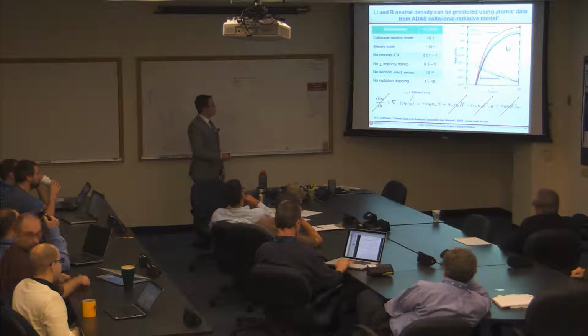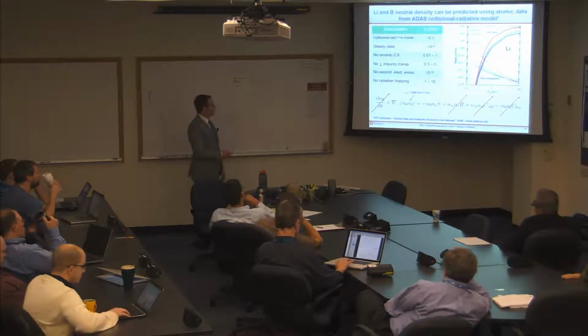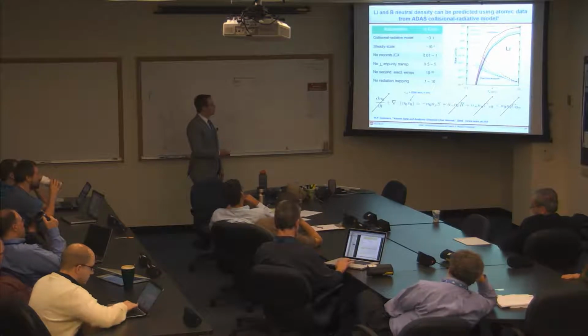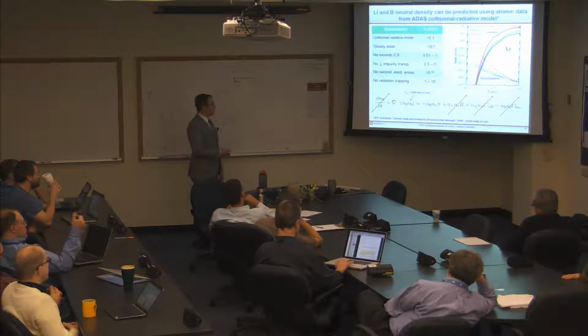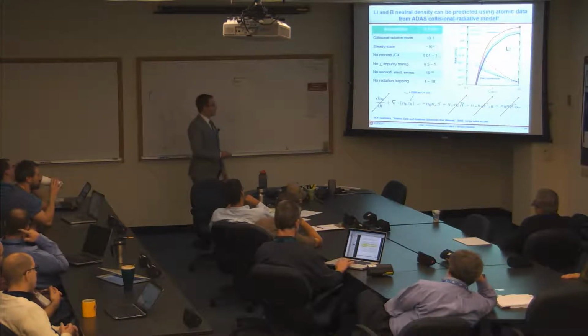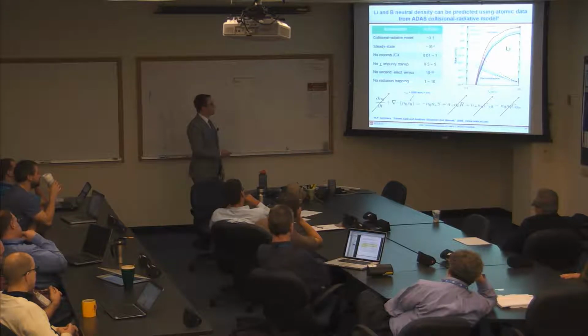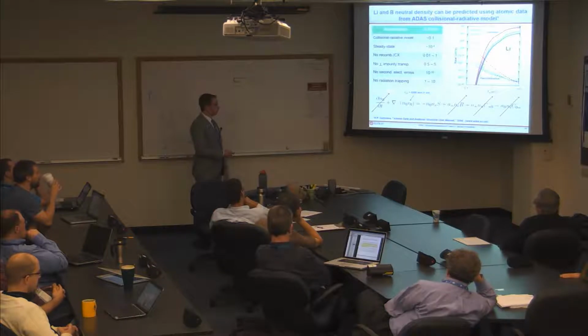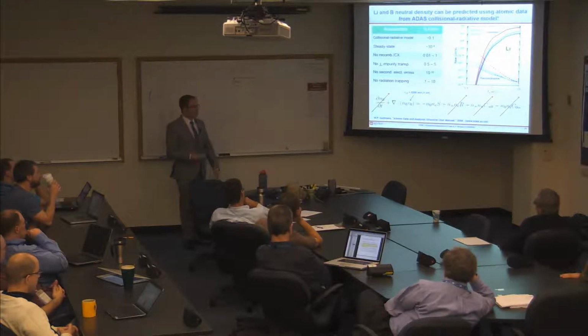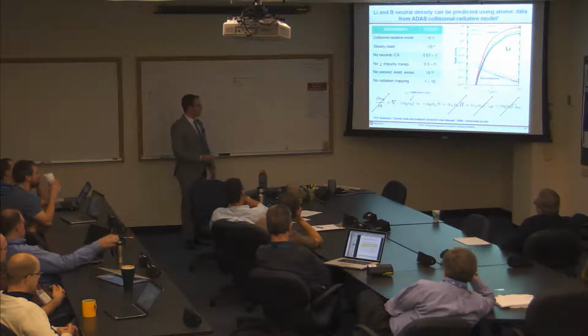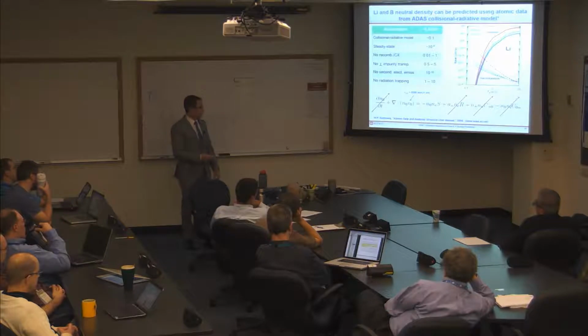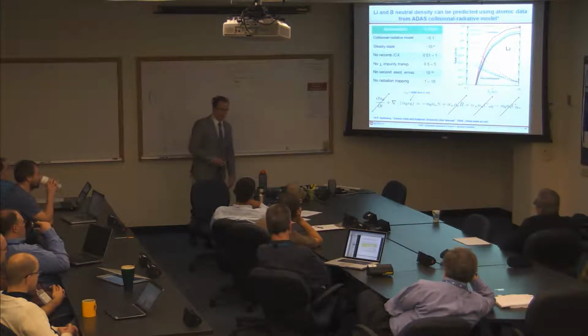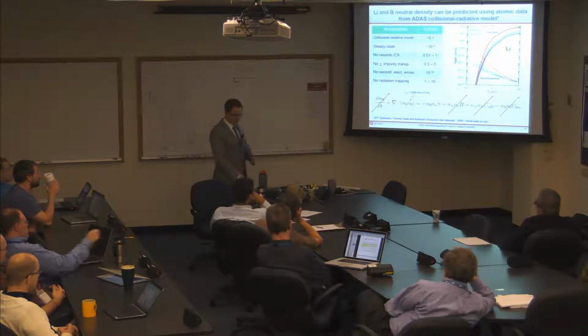So there are a number of other assumptions that we made. Using the collisional radiative model is a pretty small error bar. Steady state, I mentioned, no recombination, no charge exchange. You assume that the lithium atoms are not diffusing perpendicular via collisions. That ends up being about a 1% to 5% error. You neglect secondary electron emission, which is a very good approximation because we have negatively biased targets. And then we also neglect radiation trapping, which is a process by which an emitted photon can be resonantly reabsorbed by the impurity species, but that's really only important if you're at very high neutral lithium densities, which we were not quite at in these experiments. But it is something that you would have to worry about if you went to even higher lithium densities.